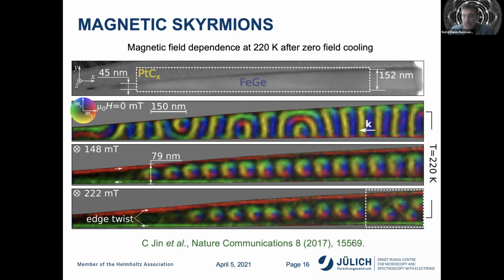These are vortex-like structures which all spin in the same sense. But if you look at the edges of the stripe, they are either red or green, and this is referred to as a magnetic edge twist. It's a signature of the fact that these are magnetic skyrmions. The skyrmions are squashed vertically on the left, and they're elongated vertically on the right.